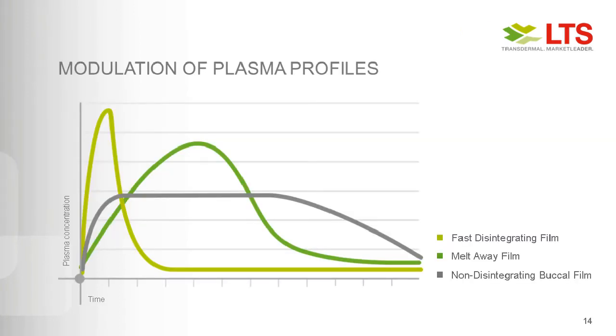When we're looking at these three different types of OTFs, we can modulate the plasma profile by using these different types of formulations. And here we have a scheme of the three types, starting with the light green for the fastest disintegrating film. When you look at the plasma concentration over time, it really would be the fastest onset of action with the highest Cmax. The second type, the green curve, is the melt-away film, and there you can see we can reduce the Cmax and delay the Cmax at the same time, but it's mostly AUC-driven. The third, the gray curve, is really something modulating schematically the delivery as a buccal patch to the oral mucosa by only that surface area. But of course, it's by far not as long as a transdermal patch, which takes days or multiple-day applications. Here we are still within a short range of a few hours, maybe tops.